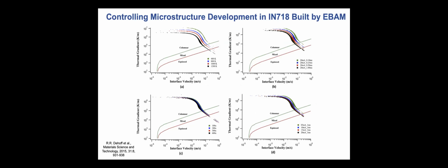Much like directional solidification, we can look at these GV conditions. Here is a nice example from Ryan DeHoff and coworkers from Oak Ridge National Laboratory, controlling microstructure development in Inconel 718, a nickel-based alloy built by electron beam additive. So we have here what's called the columnar to equiax transition, where we go from these elongated columnar grains to these more equiaxed types of grains that might have more isotropic properties.